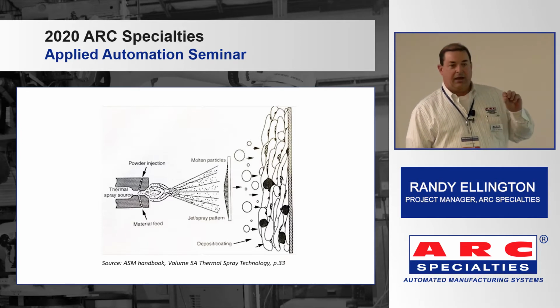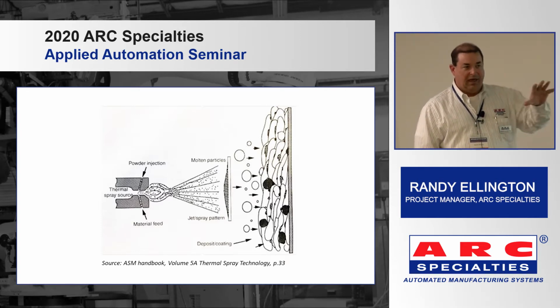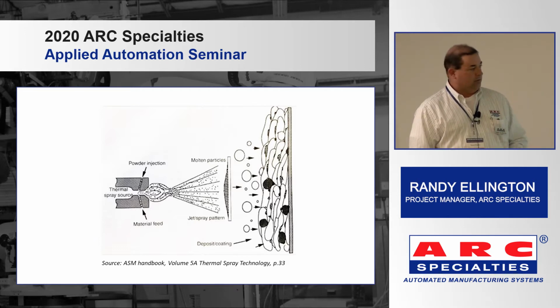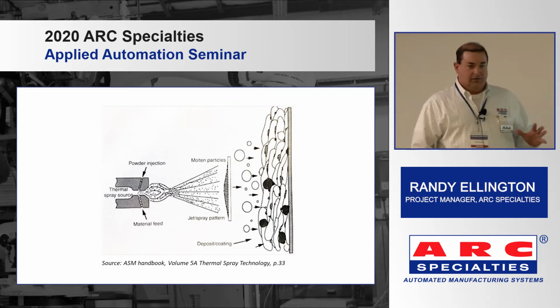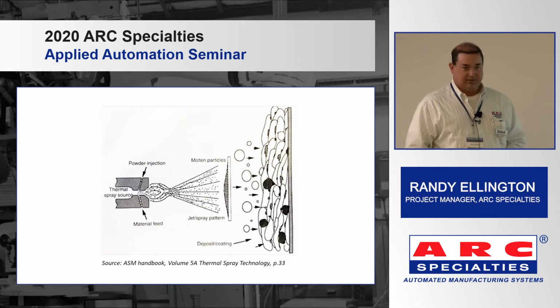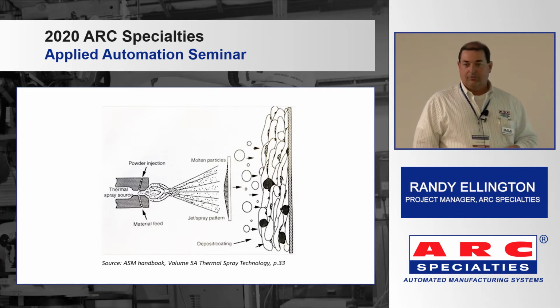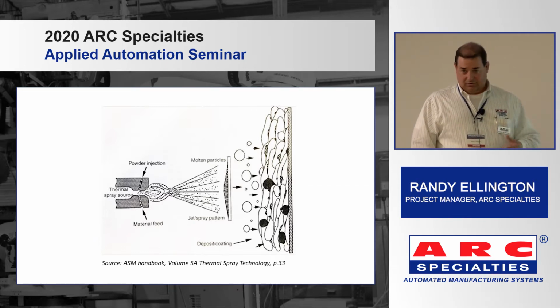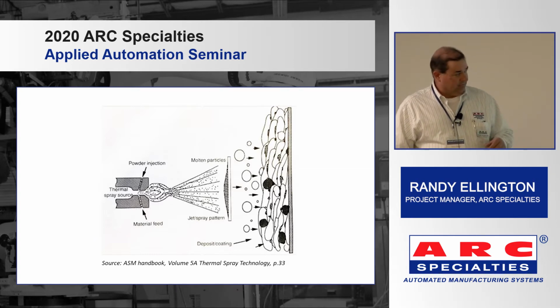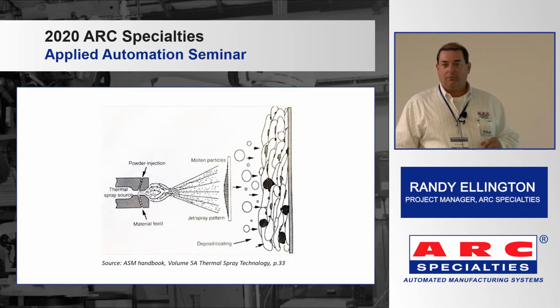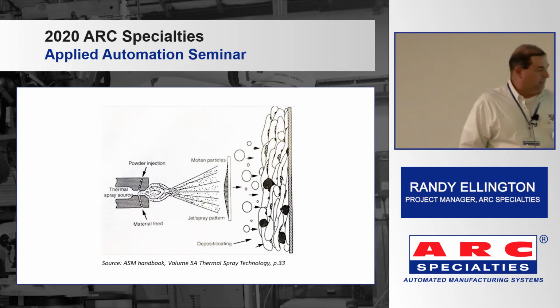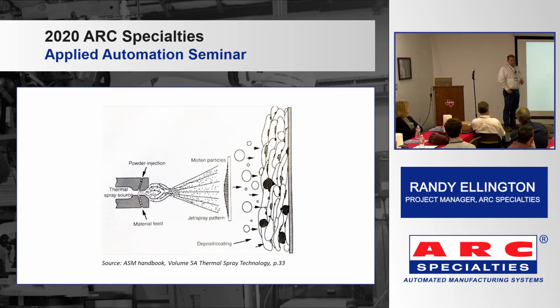Each one of those little splats, when it hits the substrate, it goes splat, and then all the other ones come in behind it. So the more kinetic energy you have, the tighter those stick together, the denser the coating, the less the porosity, which a lot of the coatings are used for sealed surfaces and corrosion resistance. So having a good tight bond between all of them with no porosity cuts down on issues with leak paths and corrosion.